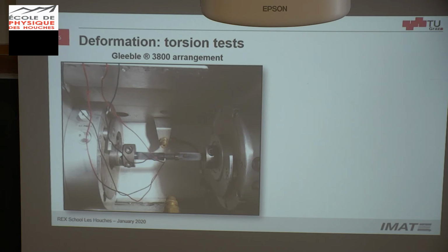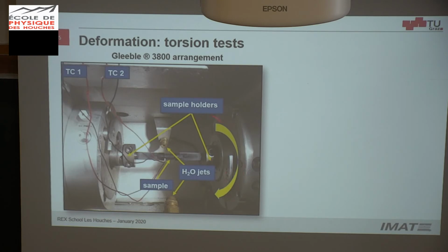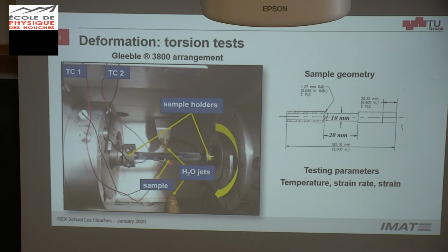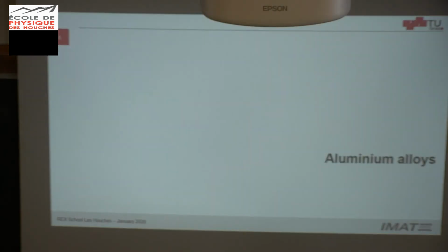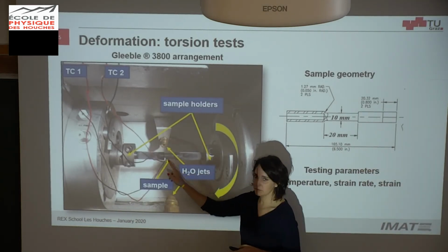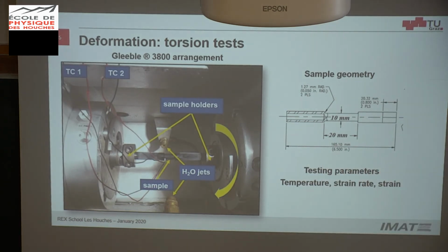In this case, this is here the sample. This is the sample holders, and one head is rotating infinitely until the material breaks. You can heat up the sample by just direct current, alternating current, sorry, by the ohmic resistance of the material. Of course, if you put the thermocouple here in the middle of the sample, and you start rotating, then you strangulate your sample. So this is not the best way.